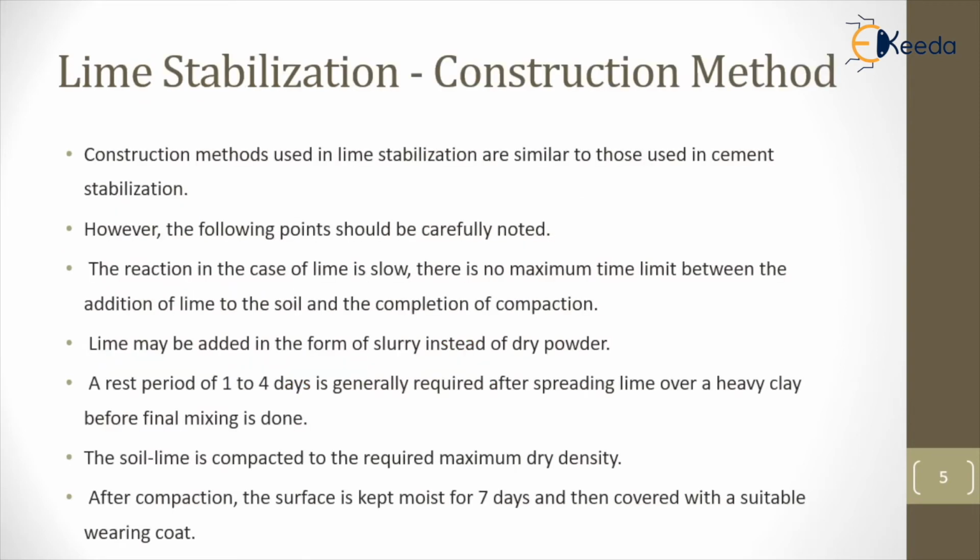Construction methods used in lime stabilization are similar to those used in cement. The reaction in the case of lime is slow. There is no maximum time limit between the addition of lime to the soil and the completion of compaction. The lime can be added to the soil in the form of slurry, not in the form of dry powder. The resting period is 1 to 4 days after spreading the lime over the clay.